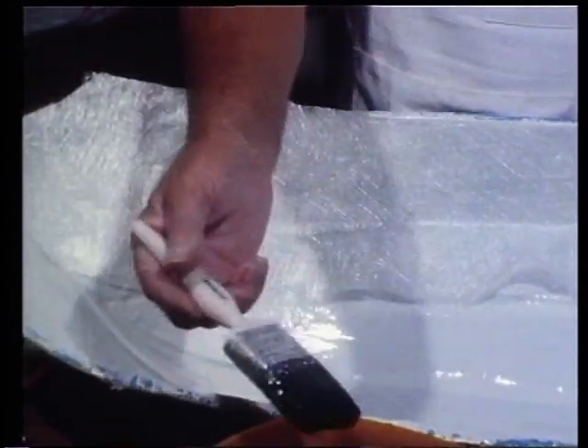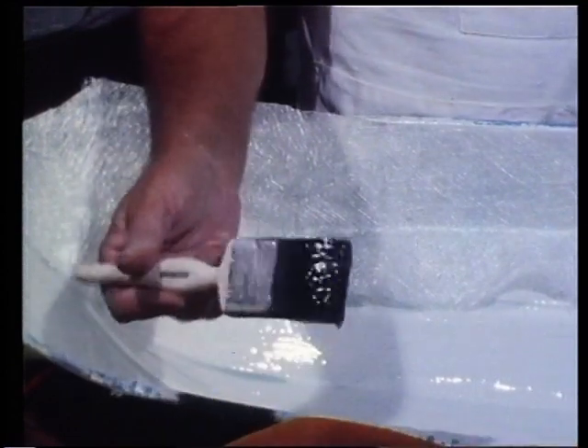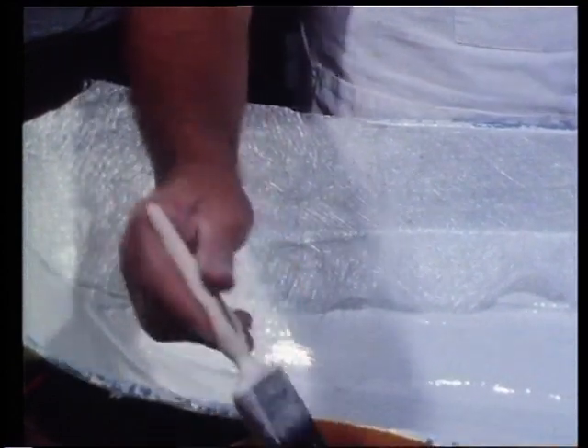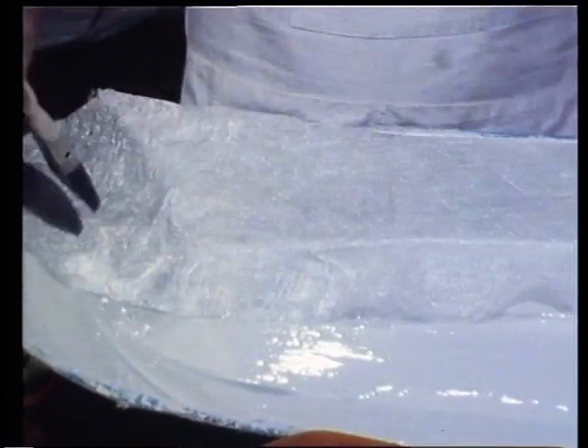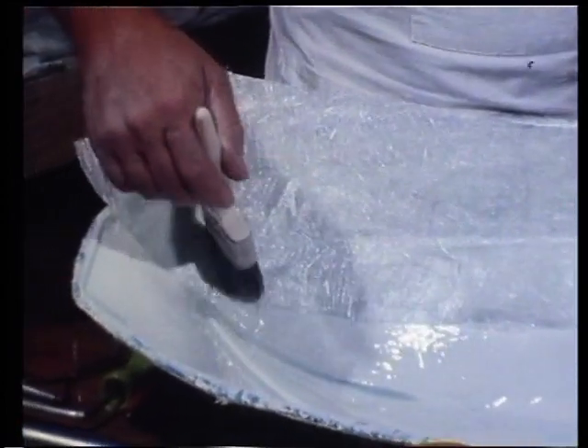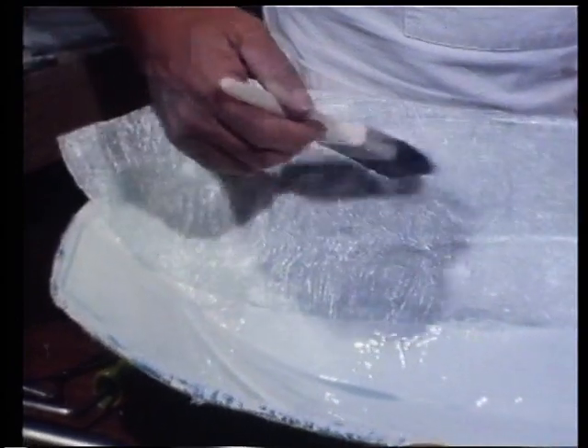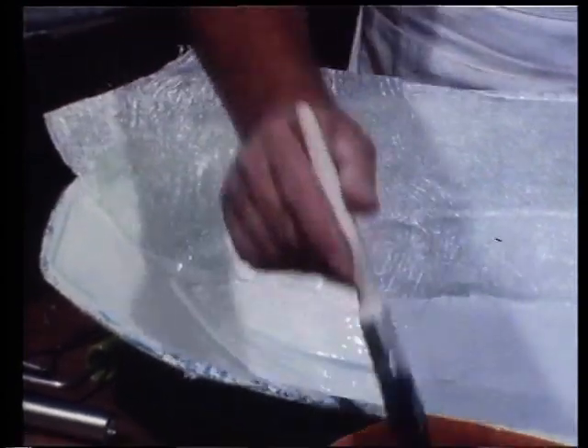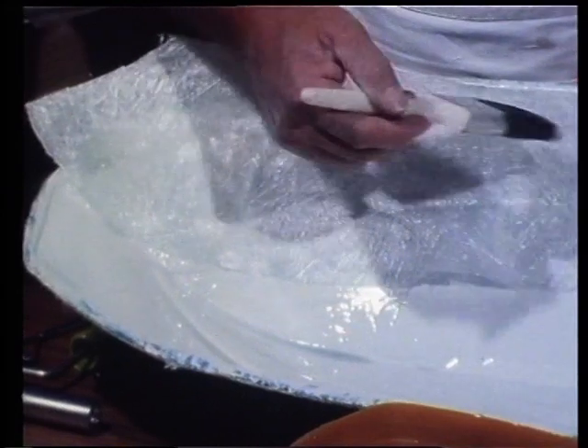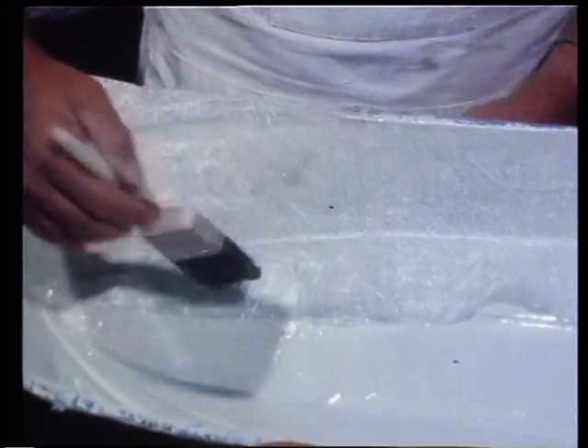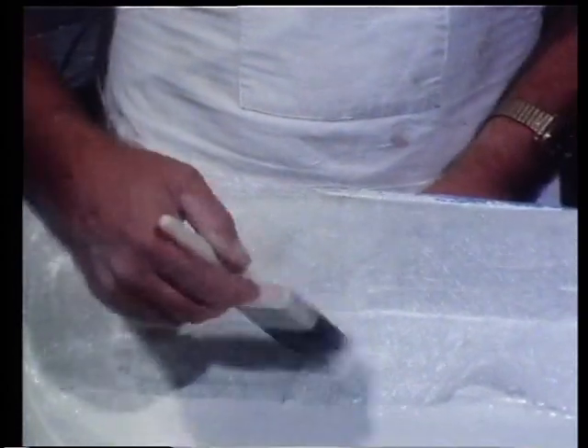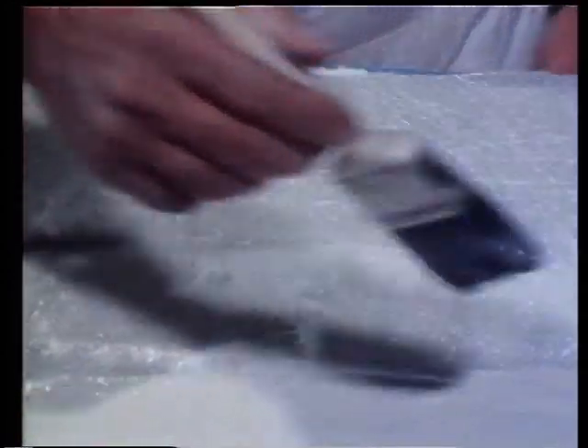The next step is probably the most difficult of all techniques for the neophyte fiberglass worker to master, and that is the stippling technique. I load the brush up with resin and I apply it in a stippling action to the glass. Now, that actually squeezes the resin out of the brush into the glass in a controlled fashion, and by using that technique rather than brushing it, I can govern the amount of resin that I apply to any particular area of the boat, and that is the major factor in making sure that you control your resin to glass ratio.